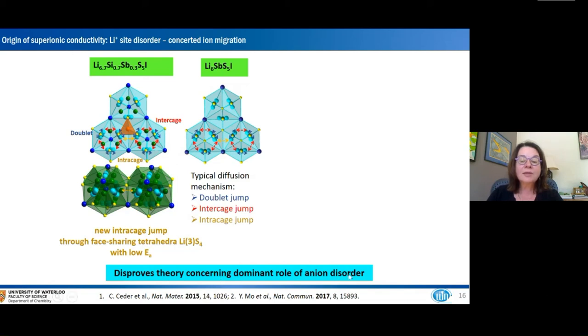So anion disorder in the iodide is irrelevant. It really is this new pathway for transport in the intercage regime that we are able to develop by literally stuffing lithium into the structure by virtue of incorporating silicon. So we go from a lithium poor regime to a lithium rich regime.